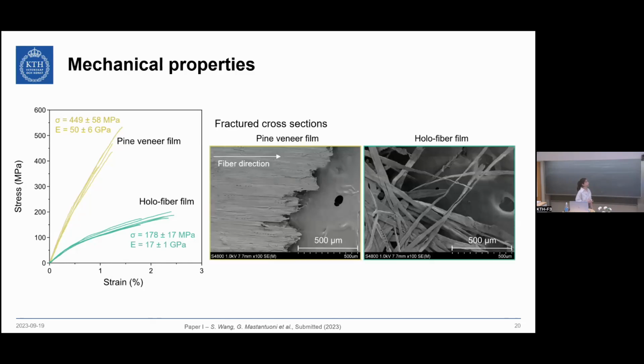The reason for this we can see from how the material actually fractures. In the aligned material, the fracture itself happens within the fibers, and this requires much higher energy compared to the random in-plane film. Here we see a lot of fiber pull-out, which means the mechanism is basically failure at the interface between the different fibers. This requires a lot less energy, and it translates into lower Young's modulus as well as tensile strength. So we've seen in this case how to achieve thin films, and that preserving the alignment can be beneficial both from an optical and a mechanical perspective.